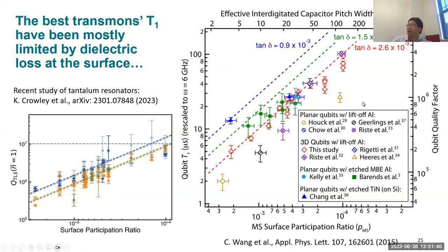So this was some aggregated data from 2015 that we plotted. And especially using the same material, the red dots, we made a bunch of transmons with varying surface participation ratio. And you can see a clear correlation between qubit T1 and the surface participation ratio. So this tells you indeed that this surface dielectric loss is a very important part of the puzzle. And this is the same for today. This is a study of tantalum resonators. And you can make a bigger resonator or a smaller resonator. And indeed, the bigger resonator, as I said, has lower surface participation ratio, and that's going to give you higher quality factor